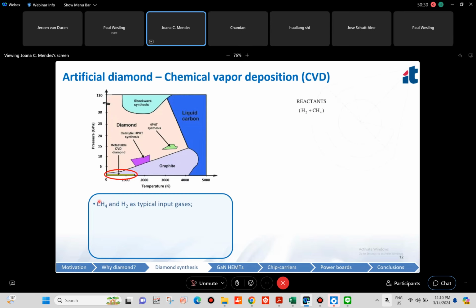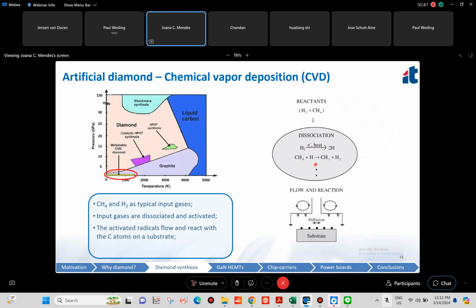So typically we have methane molecules together with hydrogen. And then we have an energy source which will dissociate the molecules. So we'll have atomic hydrogen and carbon active radicals. And then these radicals will flow and react with the carbon atoms present on a substrate, and then a diamond film will start to grow.